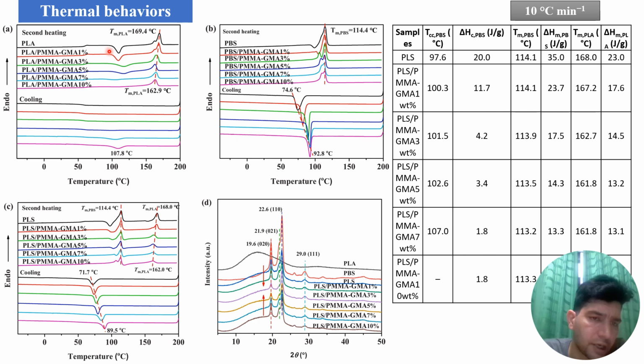the first one is the cold crystallization. By adding the compatibilizer, the cold crystallization disappears, which shows the formation of crystals. It can improve the crystallization. Here there is a peak showing Tcc of 109.6, but while adding the compatibilizer it disappears, which means that the compatibilizer helps to improve the crystallization. Looking here, the Tm of PLA is 169.4 degrees centigrade. By adding the compatibilizer, it decreases to about 162.9 degrees centigrade.